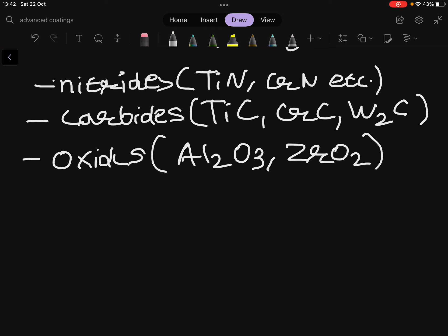All combinations of these tribological coatings exhibit high hardness values but also typically high friction coefficients. They behave well in lubricated conditions, but if we are not able to ensure efficient lubrication, we have significant dissipation of heat during sliding because the coefficient of friction lies between 0.4 to 0.9.